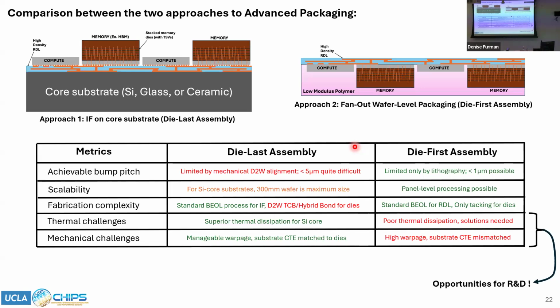However, in the fan-out approach, the polymer is organic. It has a very different CTE as compared to the silicon chips themselves. So there will be CTE mismatches and CTE mismatch stresses. And also, it's not thermally conductive, so heat extraction is quite challenging.